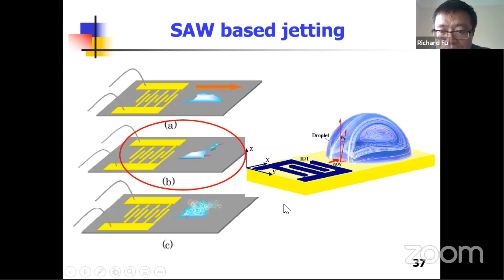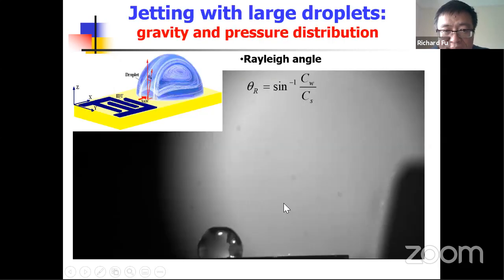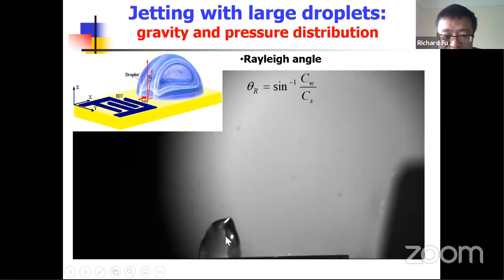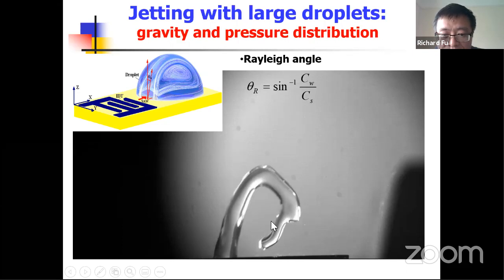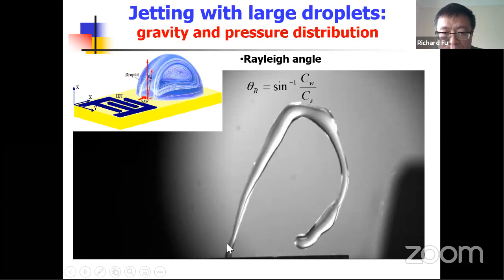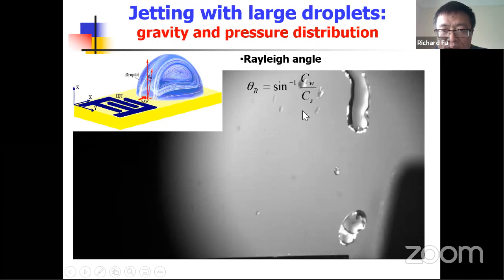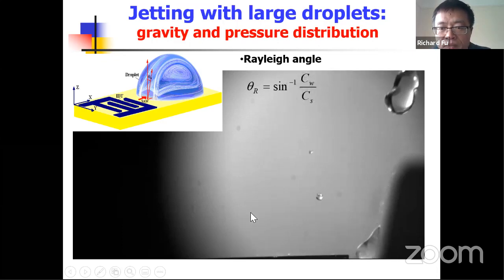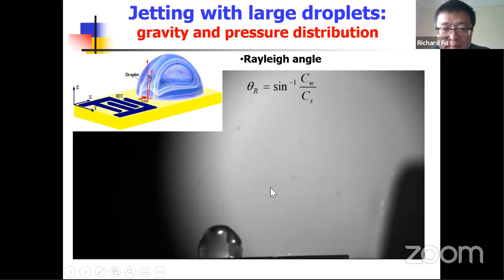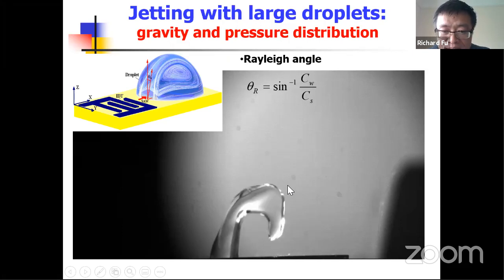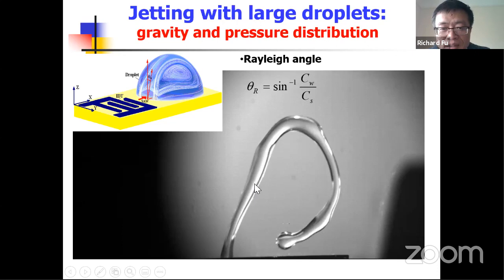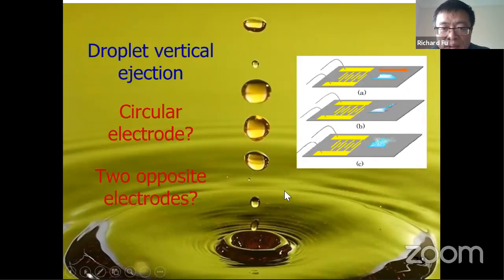If the power increases further, what's happening? Then there is no chance for the liquid to slide on the surface. The whole liquid droplet will be ejected from the surface according to the Rayleigh angle. This is a very good phenomenon. People think that we can use it for jetting, for printing. But for printing, people always use vertical jetting, right? Not the Rayleigh angle. The Rayleigh angle is quite an awkward angle.